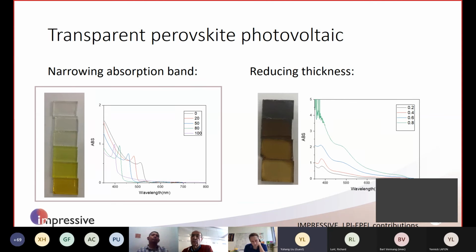During our optimization, we realized that we do not get higher voltage by reducing the absorption band, that is, increasing the band gap, beyond 2.3 electron volts, which corresponds to pure MAPbBr3 perovskite. Because of the phase issue, we cannot get higher voltage, and thus not higher efficiency, with bromide plus chloride blend perovskite.